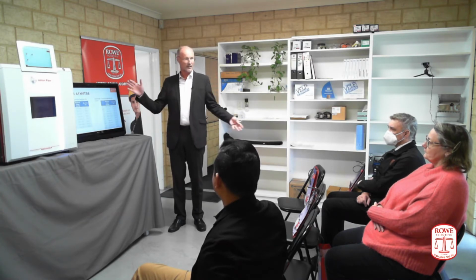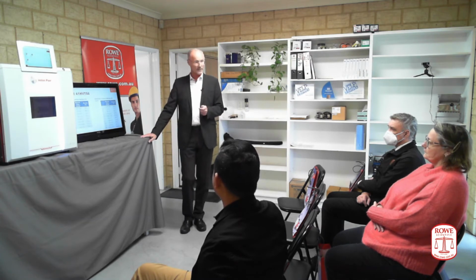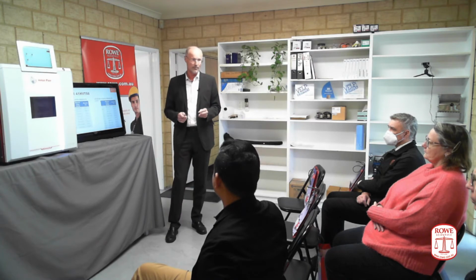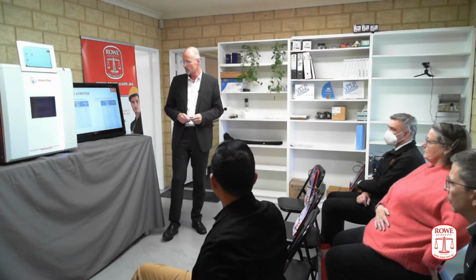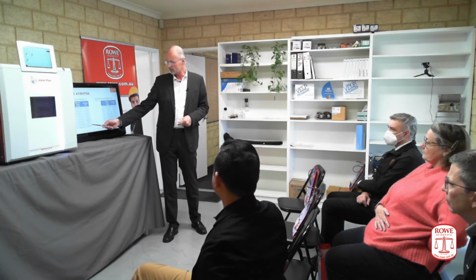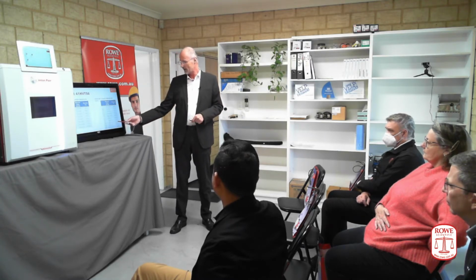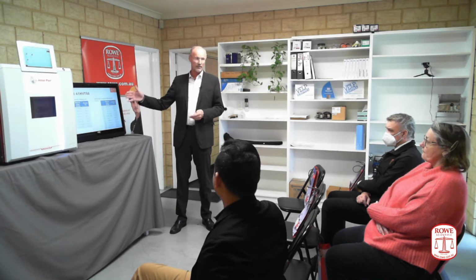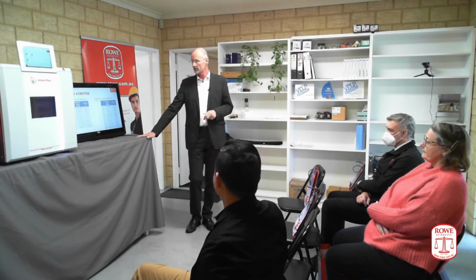Maybe you say, I'm missing a few elements. Of course, we cannot analyze all the set, but there are critical elements, for instance, like arsenic. Arsenic, you know, might be quite volatile when you cook this in open vessel digest, but look at the arsenic values here. It's found already with more than 100%. Or also with the oyster tissue, arsenic was fully recovered, although we had such venting action of unwanted CO2. So we can make sure that this functional principle of the smart vent vessels is analytically verified. And you can get a lot of application reports from Anton Paar, including analytical data that you can reproduce with this machine in your laboratory.